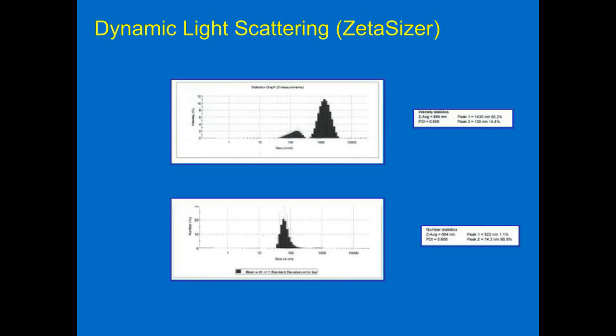It's about 650 nanometers, and this shows, and again, it didn't come out too clearly, that the smaller liposomes represent 98.9% of the total number of liposomes, and using that number, we can then calculate from the Multisizer results the number of the smaller particles that are below the range of the Multisizer.